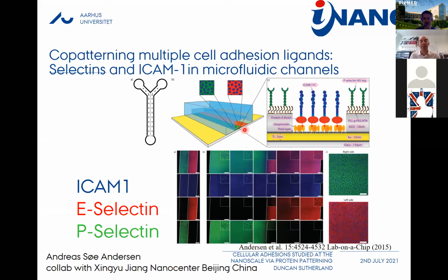Here, we're working with the same platform of having a gold and silicon dioxide chemistry. We covered the silicon dioxide with a protein rejecting chemistry, but we allow coupling chemistry between those polymers to allow us to couple something to the surface. That's the easiest way to have a protein nanopattern with 2 proteins: to have a nanopattern of one and then just fill the background with another.